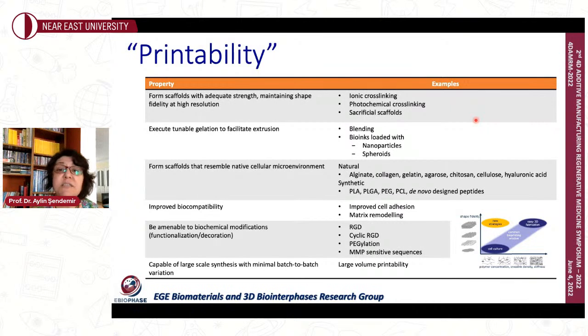Photochemical cross-linking and sacrificial scaffolds, also printing using a sacrificial scaffold, printing inside that scaffold and then getting rid of the supporting material, is a very commonly applied technique. We do use a lot of blending and addition of nanoparticles, spheroids, even cellular spheroids now are being experimentally tried to increase the printability and stability of the 3D bioprinted structures.